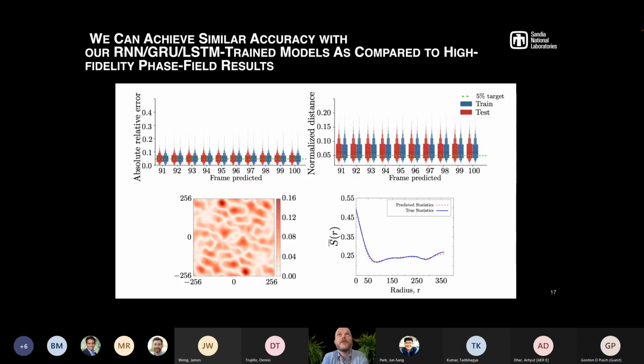And so what you see is that once your neural network is trained, you have similar accuracy as compared to high fidelity phase field results. The results at the bottom show predicted time frames that have not been seen by the network, for both the training and testing data sets. We can achieve a difference between the predicted microstructure evolution from the neural network and the direct numerical simulation phase field results of less than 5%. And this is over 10 time frames, which is a lot of time. We can also capture both the short range and long range interactions in the microstructure evolution, which gives you a very good accuracy.